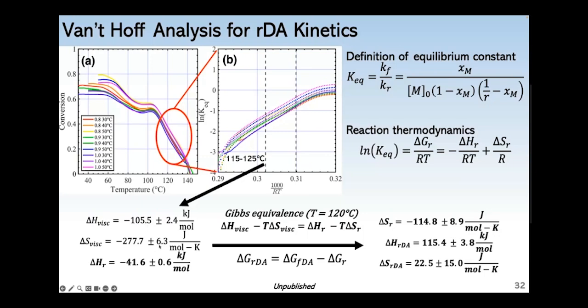Initially, though, the values I obtained for fitting a line here in this region were, to me, way too large for a typical Diels-Alder reaction. So I called them apparent viscous enthalpy and entropy. But I've also already measured the enthalpy of reaction from my earlier results. So I thought I might try just setting them equal to each other, the viscous and the reaction parameters, so that I could calculate the entropy of reaction from this equation. If I do that and I solve for it, I get a reasonable value, and then I can use this bottom equation to calculate the reverse kinetic parameters for the Diels-Alder reaction. And these were quite similar to values obtained from other kinetic studies.